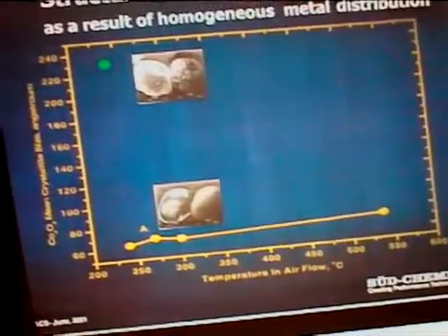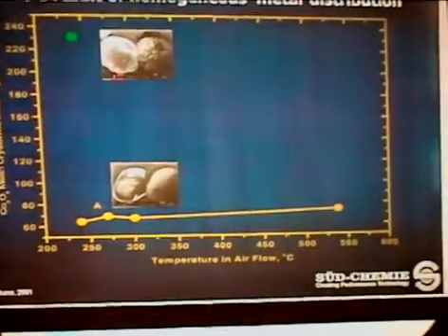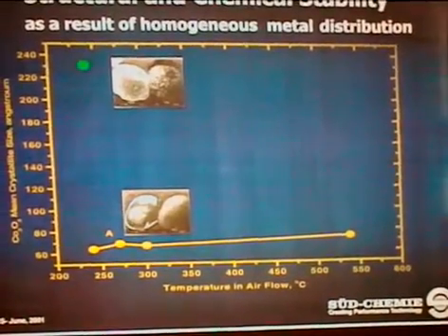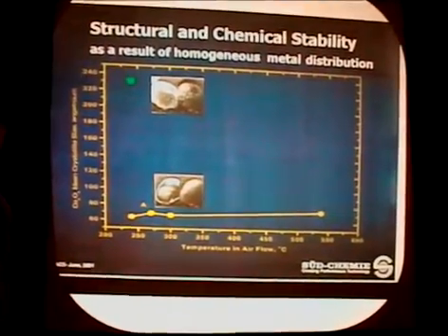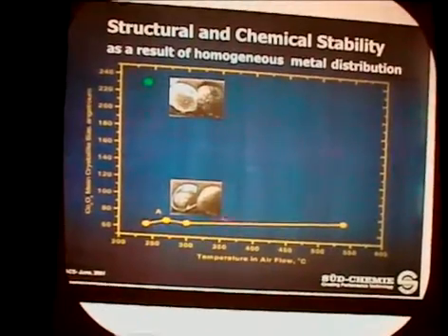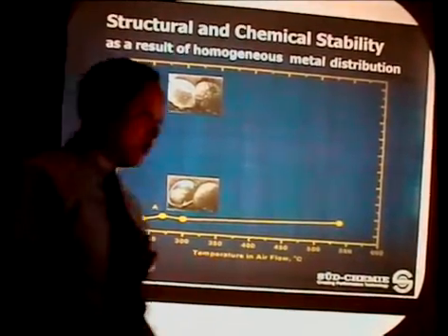looked more closely, and we put two different catalysts in a real calcination atmosphere, which is typically calcining in air, and then we increased the temperature as high as 550 degrees C. The catalyst with the rough surface and conventional impregnation method gets a larger cobalt oxide crystal size, but the one with the smooth surface, with our own method and non-acidic environment impregnation, starts with a smaller cobalt oxide crystal size and remains small even to almost 550 degrees C.